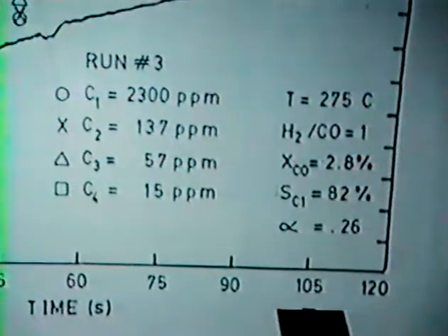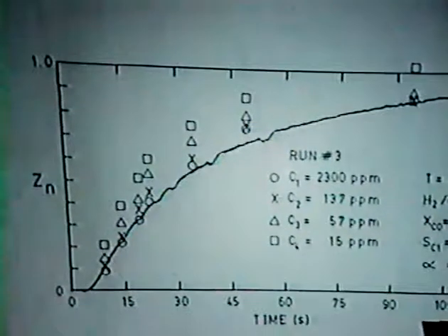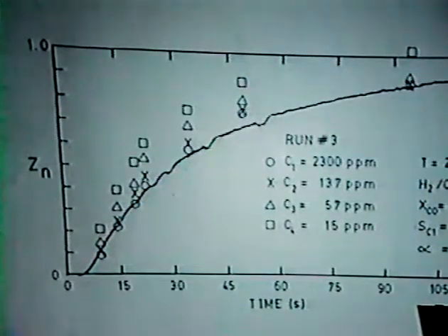Well, now, this certainly confirms the notion that there's very little carbon-13 which can be stored up anywhere on the surface in the form of partially grown chains, on nickel at least, because all the curves are close to this line, and certainly they lie above it. And of course, the precision is not incredibly good, but it's quite good. You see that in practically all cases, the experimental points are in the right order. Of course, if we go far enough over here, they all should come on to a common value at once.